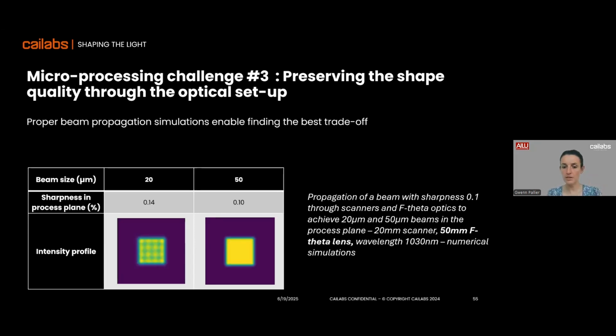So this is another example, and in that case, we just change one thing. We change the focal length of the F theta. We go for a shorter F theta, meaning it has a higher numerical aperture, and you can see it's way better. In that case, you can preserve the sharpness even of a sharp beam. When it's 50 micron, it's perfectly preserved, and it's actually not that bad when you're looking for a 20 micron beam. Then we go back to the first setup, 20 millimeter scanner and 100 millimeter F theta, but we change the sharpness. If we start with a beam which is a little bit smoother, it's not cropping, and you manage to preserve a nice beam shape up to your processing plane.